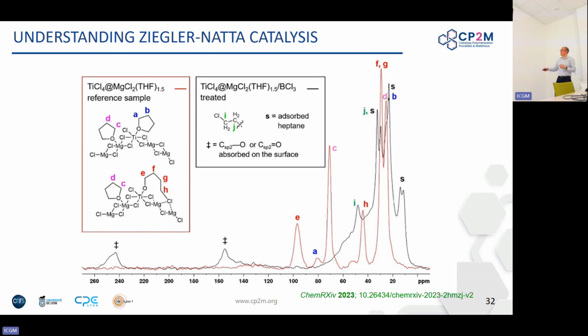This is what we showed. This is a solid state NMR with carbon, so it's a CP MAS. And it shows you that you have the characteristic signals of the alkoxide, and after treatment, they are completely gone, and you form species that are apparently on the boron, but we still have to precisely assess where they are.